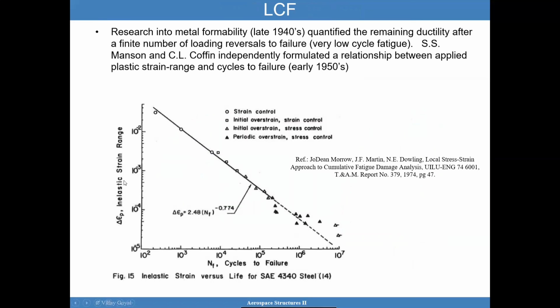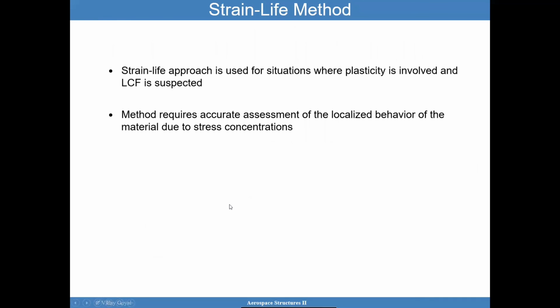And with these plots, you need to be careful. Some of these plots can be the total strain range, or it could be the plastic portion of the strain range. But bottom line, this is found empirically. And again, you're going to see here a low number of cycles to failure. With very high strains, you can have very low cycles to failure. So it can be curve fit again. Again, all this stuff is curve fit. You need test data to figure it out.